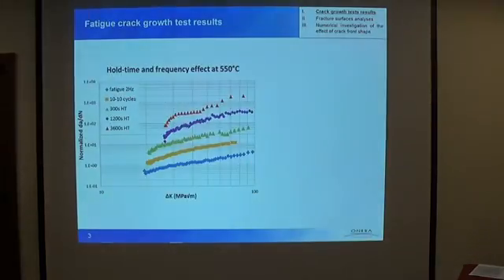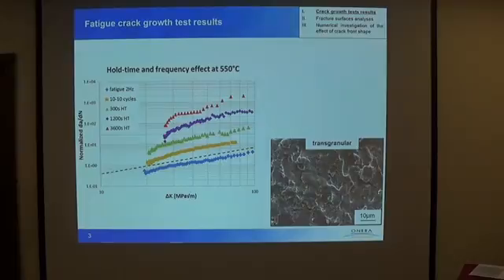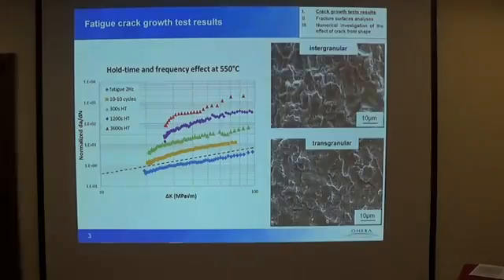Without further ado, let's have a look at the results. Here we have our reference cycle, a 2 Hz frequency sinusoidal cycle. You can see that comparing it to the 10-10 cycle, there is a tremendous effect of loading frequency. As the loading frequency is decreasing, crack growth rates are increasing. And you can see that crack growth rates are also increasing with the application of a hold time at maximum load. About the crack growth mechanism, we observed typical transgranular fracture surfaces under the 2 Hz fatigue cycle. And for all the other cycles, from 10-10 and all the different hold-time cycles, we obtained an intergranular fracture.